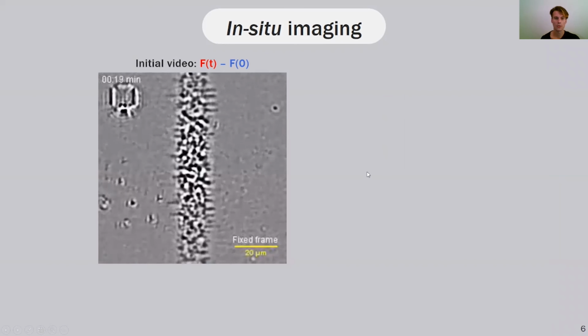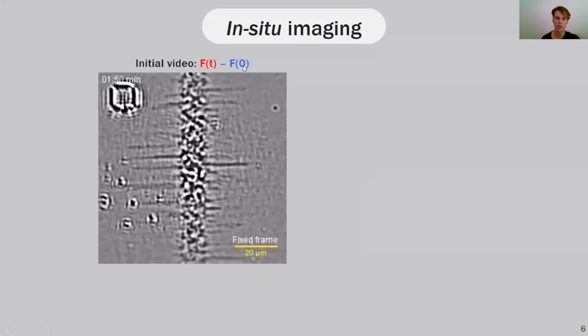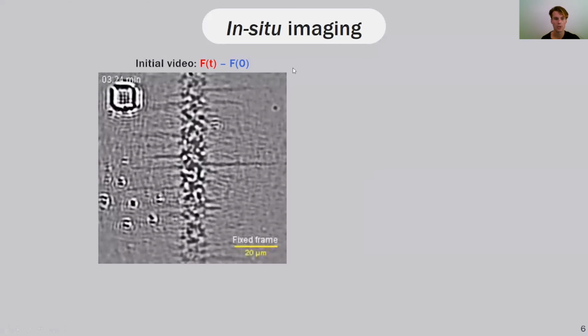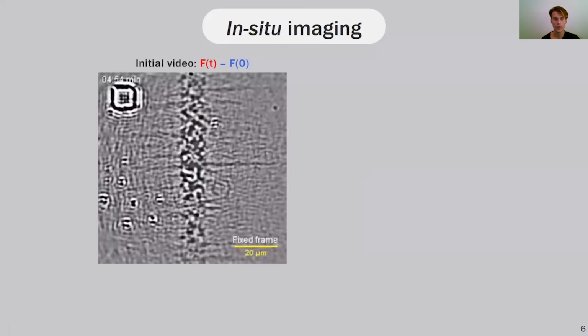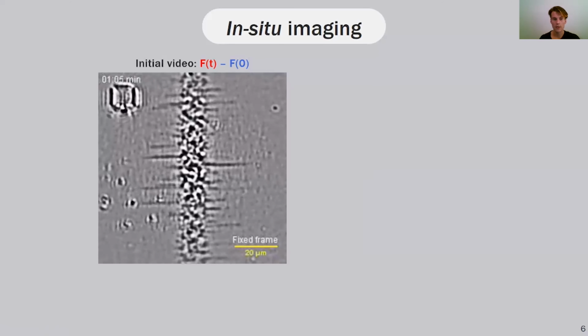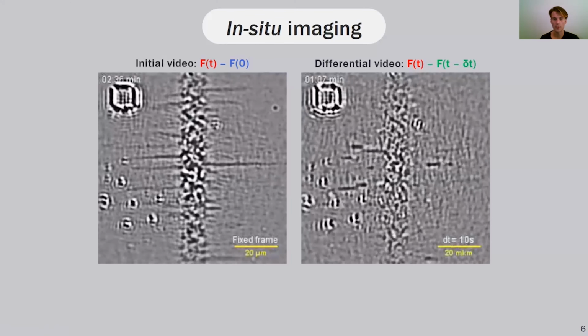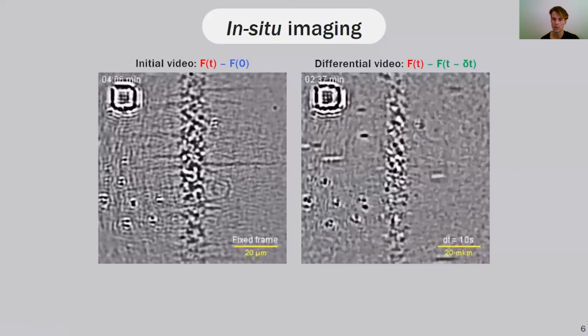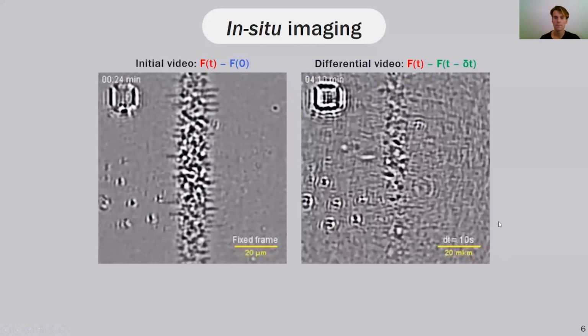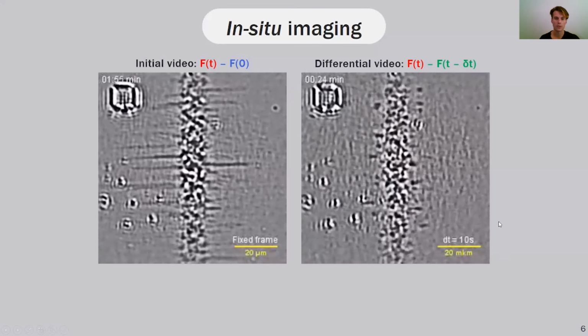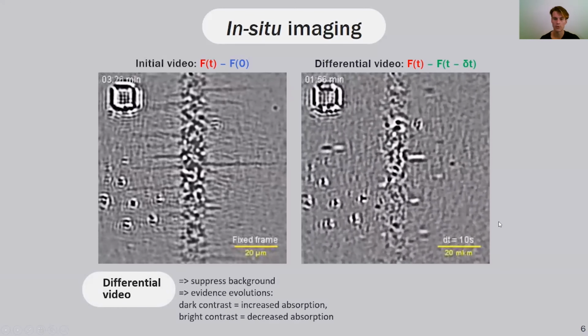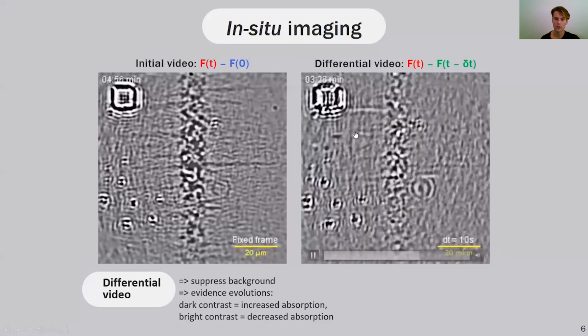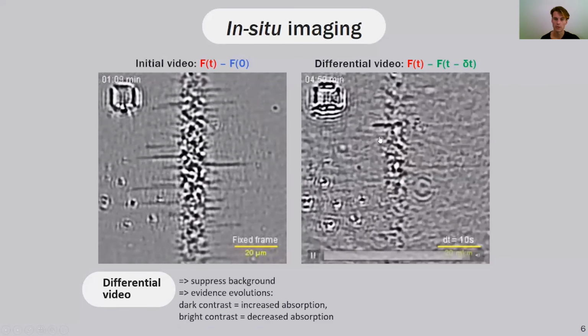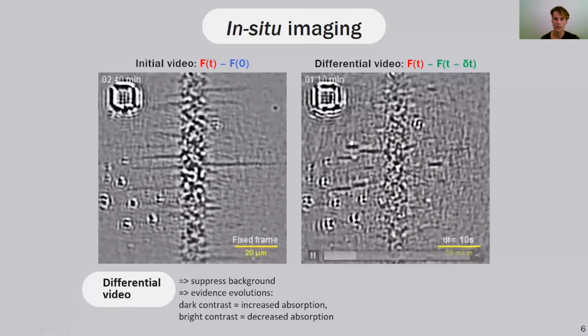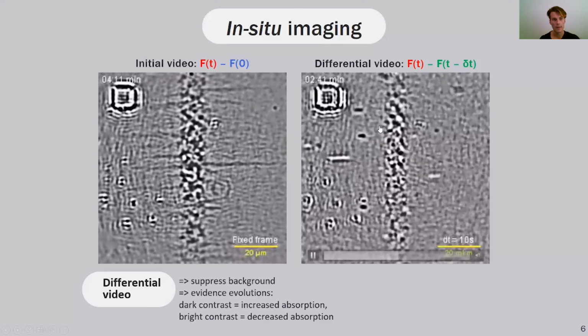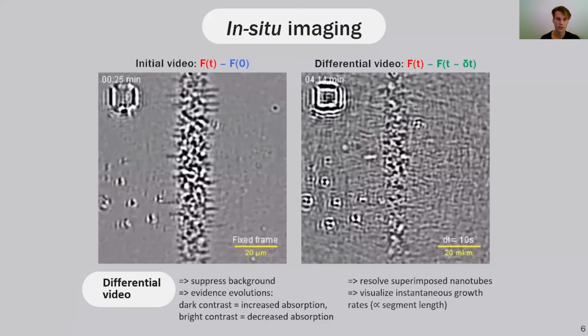One of the important stages of the treatment of the video is shade correction, and here it was made by subtraction of the initial image from the entire stack of video frames. And we developed another approach, which is based on subtraction of a frame taken several seconds before, and we call it differential video. Here, its delay time is 10 seconds. This method has several advantages, one of which is evidence of evolutions. Dark segments correspond to an increase of absorption, while bright contrast corresponds to a decrease of absorption. And the size of the segments itself corresponds to the nanotube growth rate, which is important.